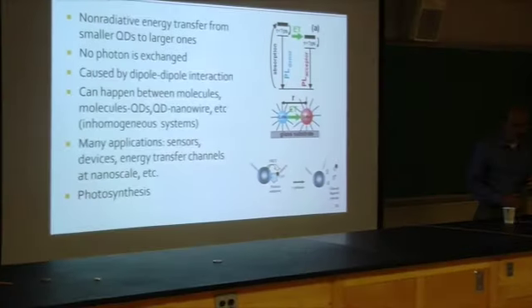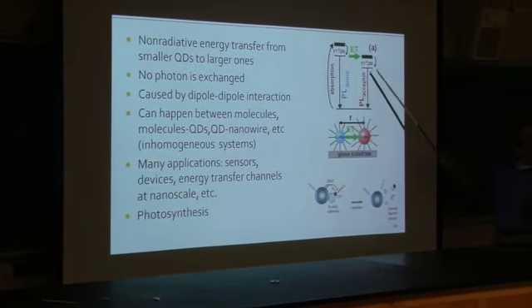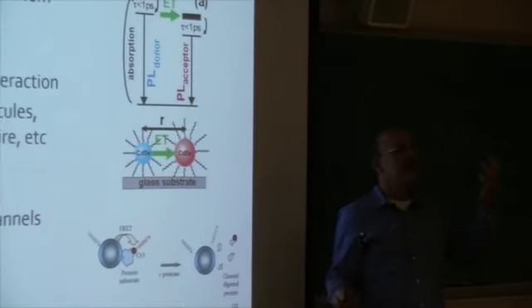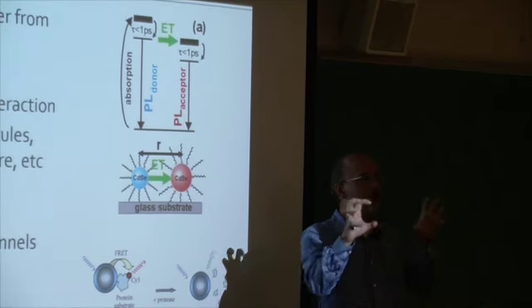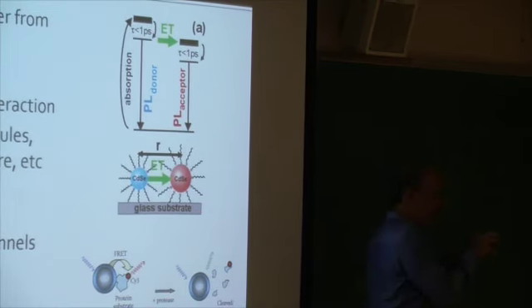So let me explain a little bit about FRET. The FRET process is basically resonance transfer of energy without a photon. If you have two quantum dots very close to each other, there is a chance that energy goes from a smaller quantum dot to a larger quantum dot without exchanging an electron, a hole, or a photon. Basically, one quantum dot as a dipole starts to oscillate, and the other one starts to grab it, and energy goes from one to the other. This is FRET, and it is very common. And it is very much used for sensor applications.